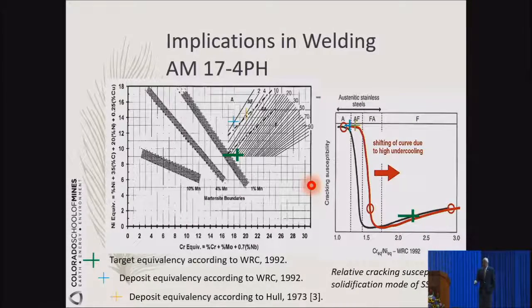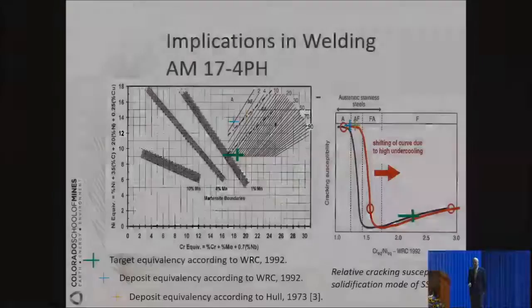Okay, and as a consequence of this change in composition, you actually change the microstructure, the solidification and microstructure as well. The expected composition from the substrate here is calculated according to the WRC index, so it positions here. It is a ferrite solidification mode. But when you have a deposit, these two deposits here, they sit up here. It may be a little bit too light for you to see, but they sit here. One is closer to austenite solidification. The other one is an AF, so austenite primary solidification and then ferrite solidification. If you plot on this diagram, they represent these diagrams here. Now, if you increase the cooling rate, then it shifts also to the right-hand side. And cooling rate is important in 3D printing because each one of those deposits is so small relative to the substrate. So there's a lot of metallurgical engineering work there.